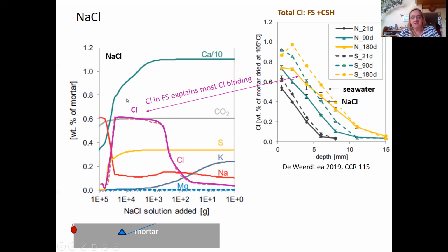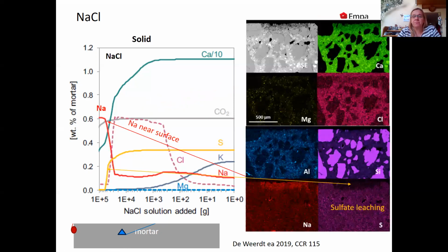And if we compare here the weight percent of chloride in the sample calculated with the measured weight percent, we can see we have a similar behavior. We see this increase towards the center, and then very near to the surface, we actually even predict a complete leaching of that. The values themselves do not completely agree because we only calculate friedel salt, but in addition, we also have bound chloride in CSH, which will contribute to the measured experimental data.